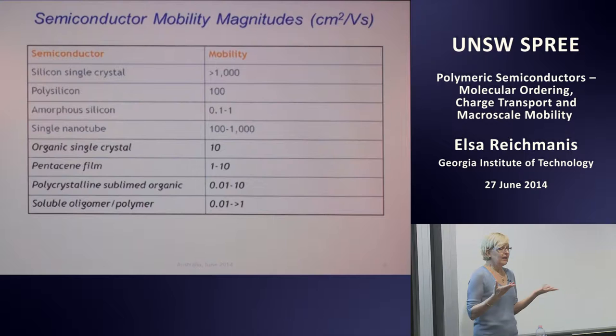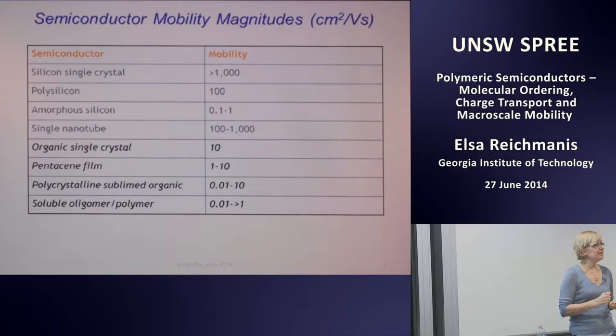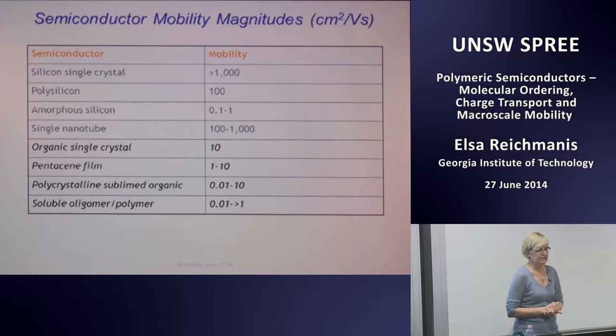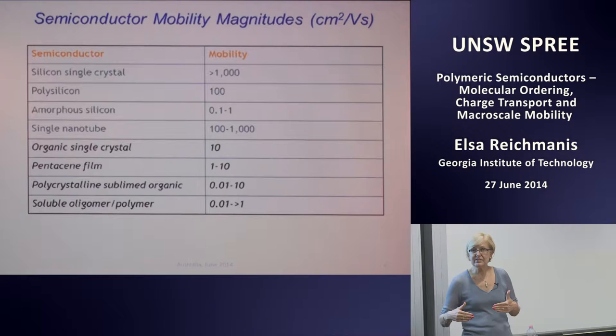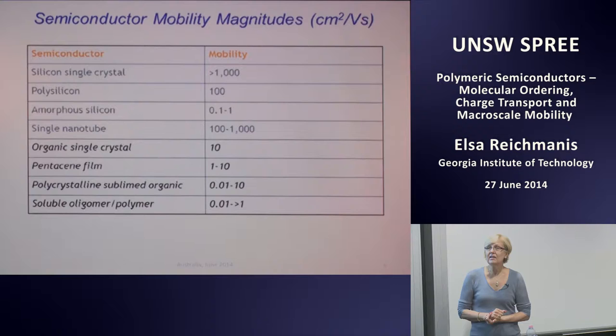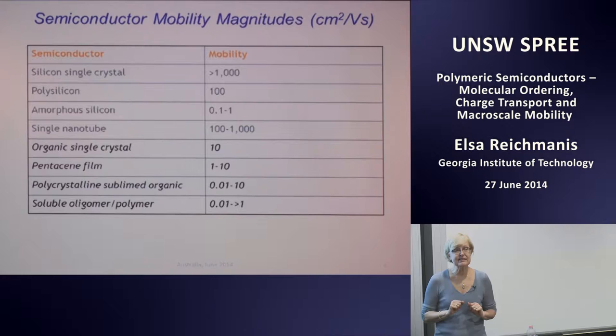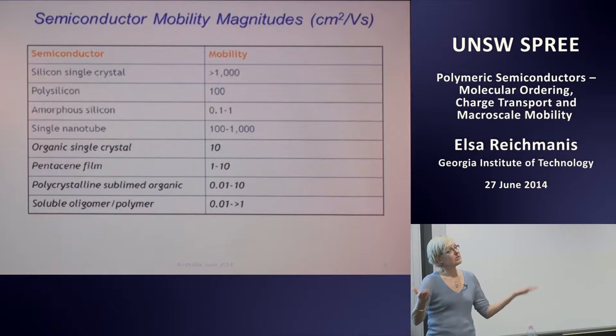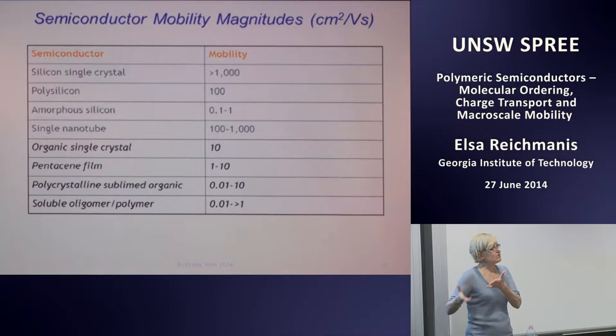All right, but then if we look at amorphous silicon, it has a mobility only in the range of 0.1 to 1 centimeter squared per volt second. And if we look at organic and polymer materials, we certainly see that some solution processed organics and polymers are now being produced with mobilities in the range of about 0.1 to greater than 1, so that they really are in the range of where amorphous silicon is. So we can start thinking about applications where amorphous silicon is typically used, but perhaps we can now think about using polymers or organic materials that are going to be flexible. This would provide for alternative applications where silicon cannot easily be used.